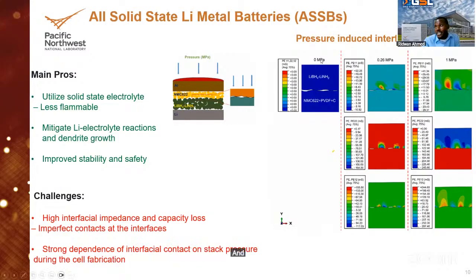And as we can see from here, if you start from 0 megapascal of pressure, for contacts, you see that space there. But when you increase the pressure to 0.26 megapascal, that improves the contact. And the strain is not so high. But when you go to 1 megapascal, even though you have improved interfacial contact, you can see that the strain is so high. And they have gotten to a level where they can induce cracking, mechanical failure within the electrode, which is not good for the battery.